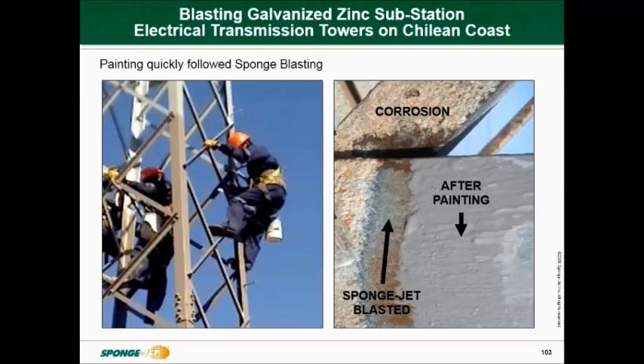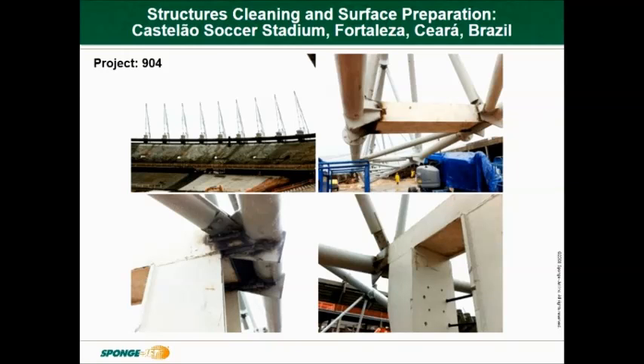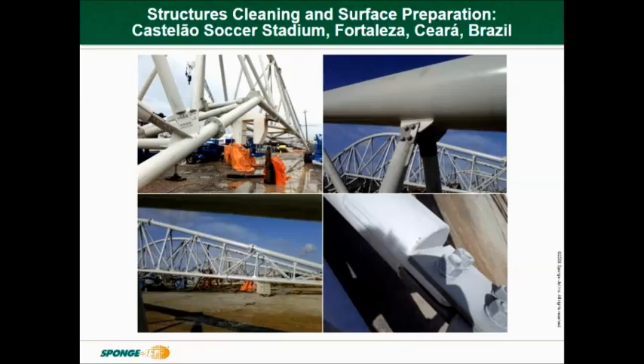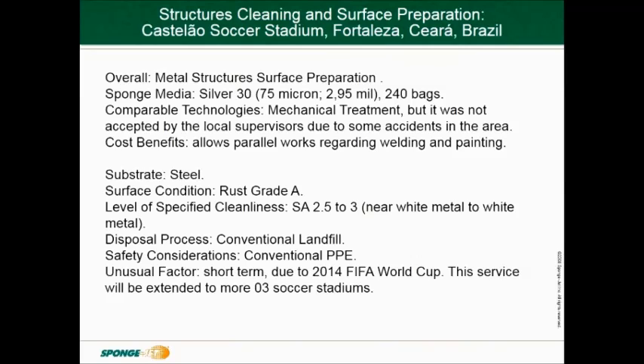Now we'll look at some outer structures. Project 904, a huge project in Brazil where the scope was to blast the connection and intersection points of the stadium structure. All the towers, verandas and sections were removed and brought down to ground so that they could be blasted out of a cherry picker, and the ground was covered with huge tarps not to contaminate the ground. Shown here is a series of pictures so it can offer you some size of the actual project itself. The media used was silver 30, and the project consumed 240 bags. That's 4,344 kilos, around 4.3 tonne. And if the consumption rate was based on our matrix, which we usually use 3.6 kilograms per square metre, the job total square metres to be blasted would be around 1,200 square metres.